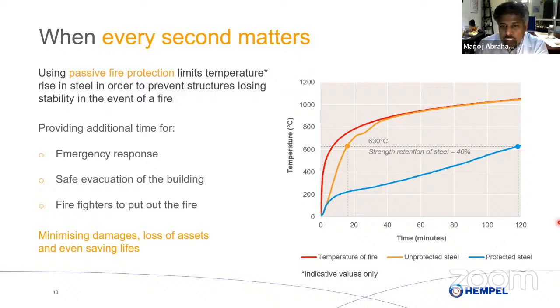So you've got 2 hours. We can change it. It can be 60 minutes, 90 minutes, 120. Sometimes we have worked on projects even to 3 hours of fire protection. So you can see that you still have 40% load carrying capacity. Therefore, the structure does not collapse. And that is how you protect it.